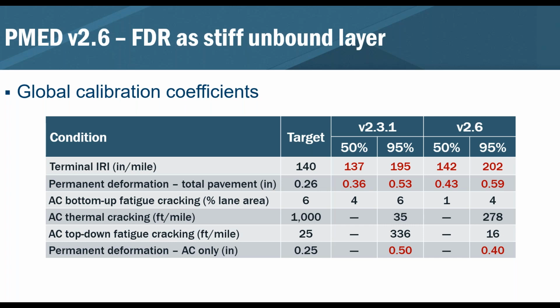And with that, the rutting difference between 2.3 and 2.6 is not huge. There is a little bit of a difference, but I don't think there was a big issue or big concerns. Certainly the total permanent deformation in the AC layer is a little bit different. It was 0.5 in version 2.3, and now it's 0.4 in version 2.6. Based on the calibrations and the model modifications that they made, that probably makes some sense, putting a little bit more deformation in the underlying layers, more so than the asphalt layer. The thermal cracking, interestingly, on version 2.6 is almost 10 times what it was in version 2.3. More likely, that's the impact of having the climate data files changed from the previous version to the MERRA values that they're using now.